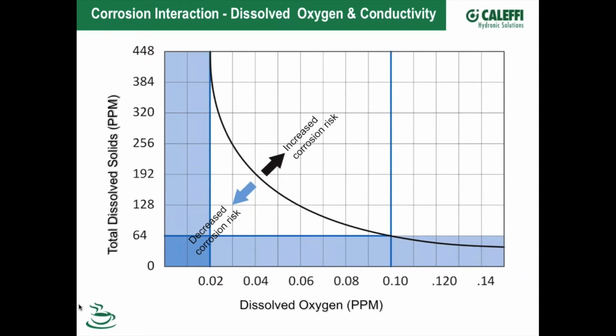So this is an interesting graph that explains the role of dissolved oxygen in water and the fluid's conductivity. The two work together, and they interact in terms of their combination effect on whether or not you have a chance for corrosion in your system. So along the bottom axis, you see dissolved oxygen concentration. And this is in parts per million, which is the same as milligrams per liter. And so that's along the x-axis. Along the y-axis, you see total dissolved solids in parts per million.